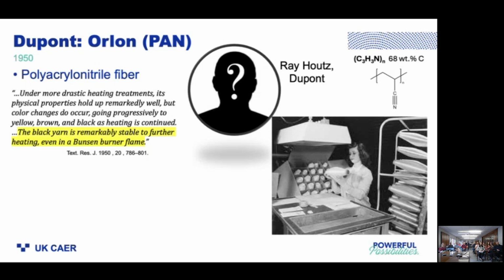Ray Houtz was a chemist there who described that he could see the fiber change color as it was heated, from white to yellow to brown to black, and that the black yarn was remarkably stable to further heating, even in a Bunsen burner flame. This gave insight that this fiber too could be of great interest as a carbon fiber.